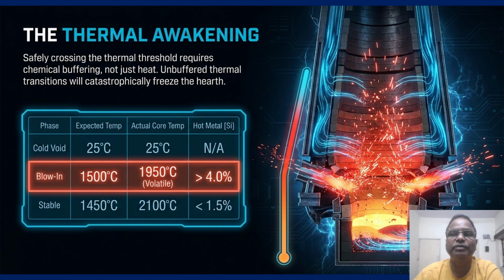So next slide, which is especially about the thermal awakening. During blow-in, we use very high thermal input to dry the burden and heat the hearth quickly. This creates high silicon, so we must manage the chemistry carefully from the start only.